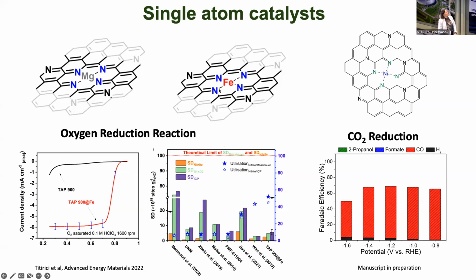Now, it turned out we've been testing the single atom catalysts with iron and nickel also for CO2 reduction. I didn't want to talk about this. I just put this slide in very last minute. But it turned out that when you use nickel at a single site, you don't make much hydrogen. You make a lot of CO, which is useful. I mean, it would be nicer if we could have C2 products. And so what we're doing now, we're taking this catalyst and we hybridize it with some copper oxide nanoparticles to see if we could actually make better products. There's still work in progress.